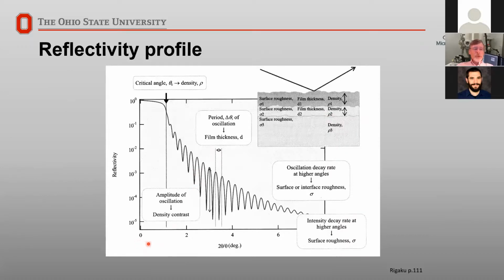This is from 0 up to about 6 or 7 degrees that you're seeing. Our normal theta, 2 theta scans are usually going up to 80 or 90 degrees 2 theta. So here, starting at 0, we are getting total external reflection of the X-ray beam. And then once the beam starts to penetrate, we start to see these oscillations in the scan. And the spacing of the oscillations tells us the film thickness.